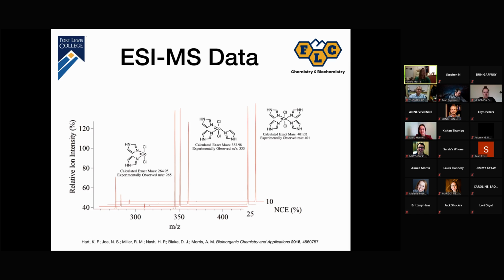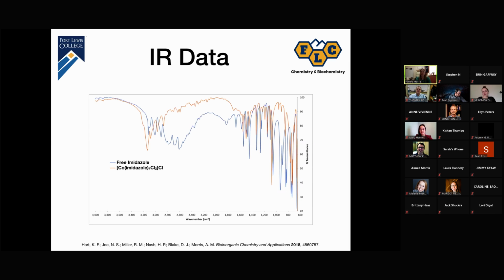And so I was working on submitting this to a journal, and one of the reviewers really wanted to see IR data. And I was like, okay, we can do that. And so the IR data, again, just shows the difference between the stretching frequencies that you'll see for free imidazole, and when it's bound, what you really lose is the hydrogen bonding vibrations that exist around 2800 to 2400 centimeters to the -1 in free imidazole, and you see this shift happening. And so this has been observed in some other cobalt imidazole complexes as well, and so just further evidence that it is in fact bound.